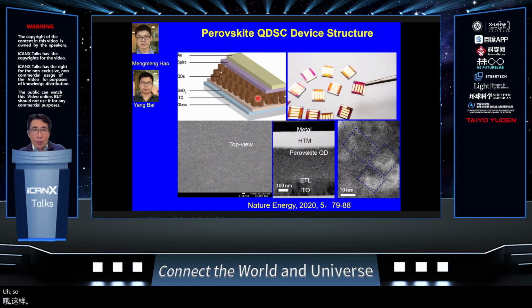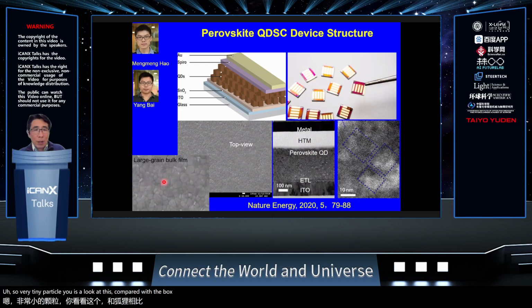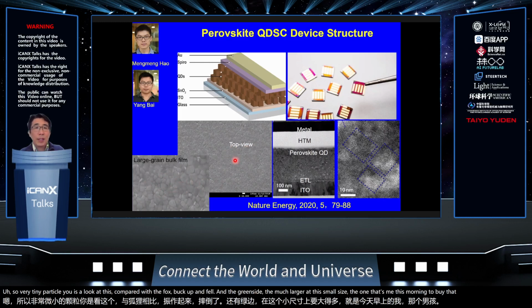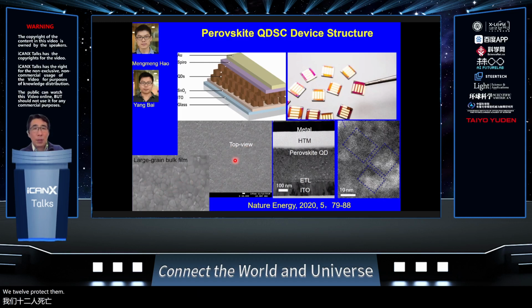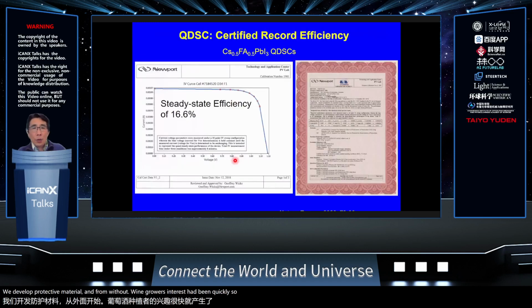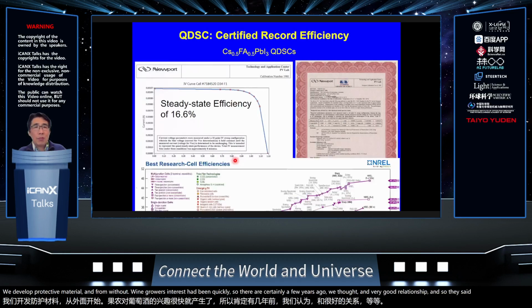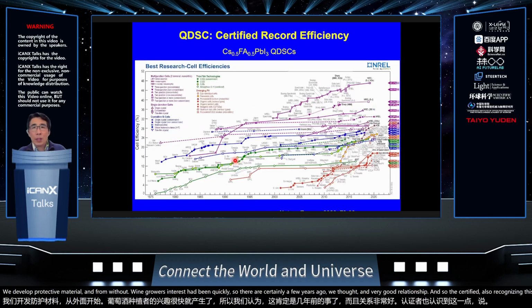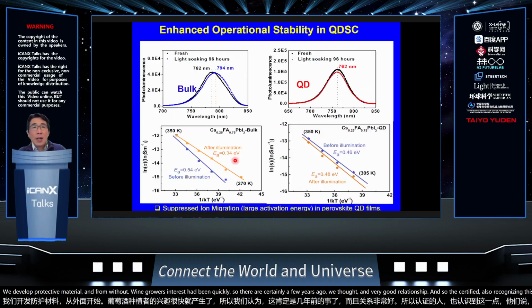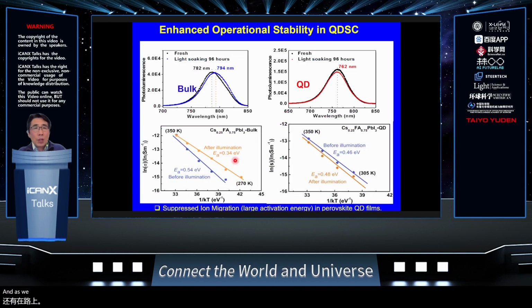very tiny particles. If you compare this with the bulk film, the grain size is much larger. And this small size means it is surrounded by the surface ligand, which will protect the material from migration happening quickly. Fortunately, a few years ago we got a very good efficiency, and it was certified, also recognized in NREL's chart, but I think we are more interested in the stability of the material.